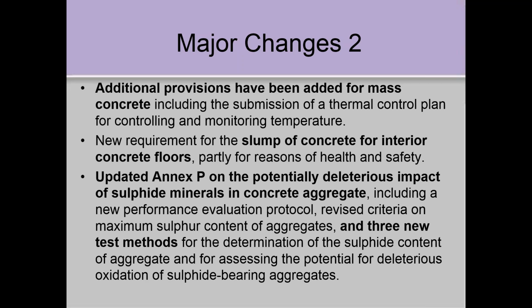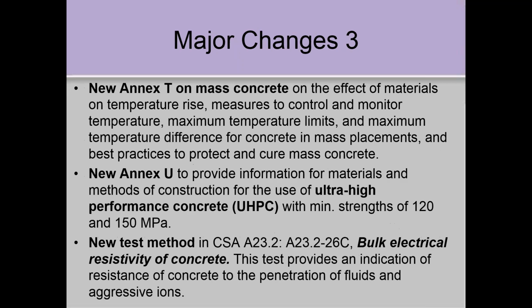We got new requirements for slump of concrete for interior concrete floors, updated Annex P on potential deleterious impact of sulphide minerals in concrete aggregates, including some new test protocols related to that. And this has to do with a big problem that happened in Trois-Rivières in Quebec over the last 5 or 10 years, where huge durability problems, and I'll talk more about that later. So there's some new requirements for testing aggregates, which will impact on aggregate suppliers across Canada, and I'll talk about that. And I said there's a new annex on mass concrete, and the new Annex U on ultra high performance concrete.